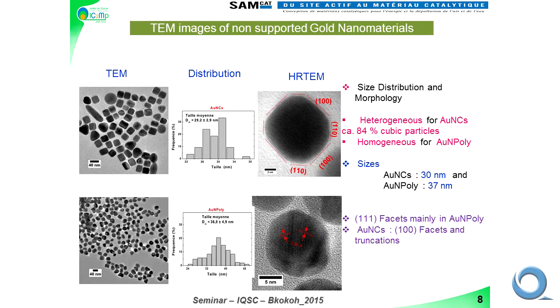And if we wanted to discuss this kind of catalyst, for example, I give you here the TEM image, the distribution we calculate, and the HR-TEM. If you see very well, it is the cubic one. We have a histogram to show the size distribution, for example. We say that we have more than 80% of nanocubes, which is heterogeneous because it's not 100%.